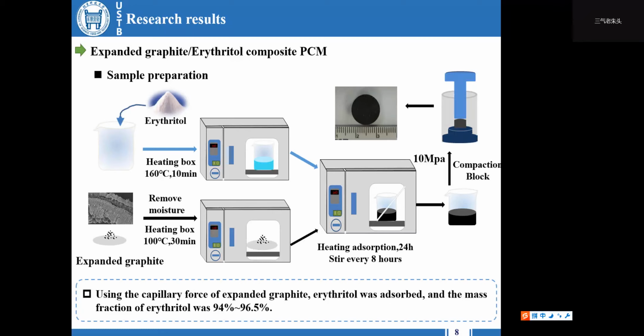The phase-changing material is erythritol, which has the advantages of high latent heat of phase change, good cycle stability, and no toxicity. Expanded graphite is selected as the porous encapsulation material, which has the advantages of high thermal conductivity, high loading capacity of phase-changing materials, and reduces the subcooling of phase-changing materials. The preparation process is as follows.